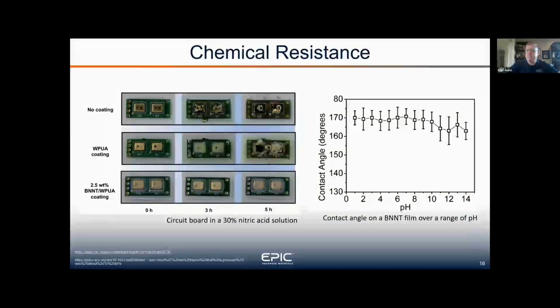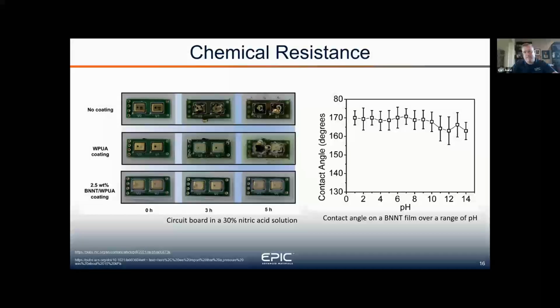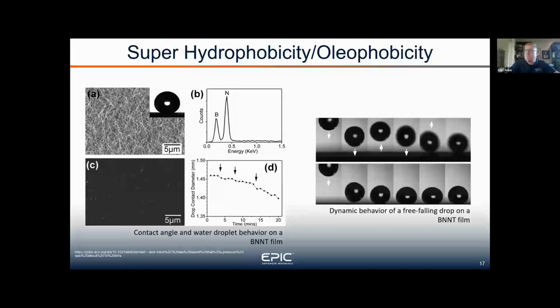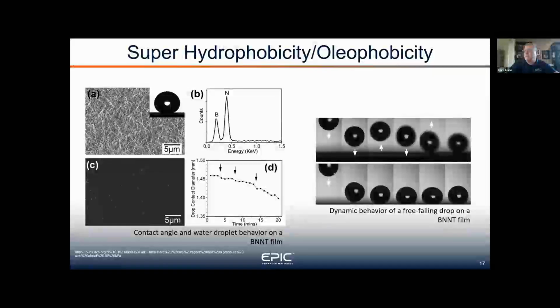Chemical resistance. Here you have 2.5 weight percent of BNNTs added into a waterborne polyurethane with a 30% nitric acid solution. The pictures tell you a clear story. After 5 hours, there's very little damage to the coating that's covering the electronics. We believe this to be based on the outer layer. Think of the outer skin layer of the polyurethane getting taken away by the nitric acid, exposing the BNNTs that then create a high contact angle over an incredible range, or the entire range, of pH. And this same property helps with hydrophobicity and oil phobicity.